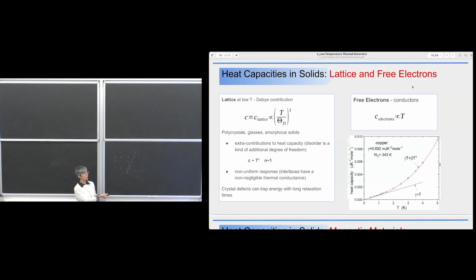No, this gamma is the electron contribution. In metals, I was taught by solid state physicists that they generally tend to form crystal, single crystal. So maybe this is not exactly a single crystal. This is a plot that I've grabbed from the web, just to give you an example. In this example, it is assumed that we have only two contributions. One is the Debye contribution, and the other is the electron contribution. And so copper is not a good absorber for our detector.